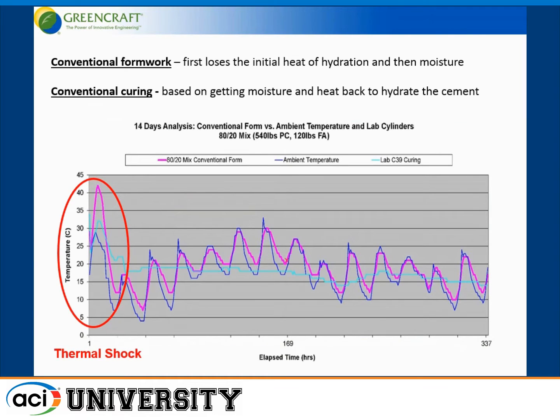Here's a chart of a project that we did in Atlanta. What we have here is conventionally formed concrete. There's a disconnect, in our view, between the formwork being simply used as a mold, which in essence it is, and the formwork being to some extent the environment in which you place the concrete in its infancy. And what we have here is an 80-20 concrete mix, 540 pounds of Portland cement, 120 pounds of fly ash type F, and you place it in the form, and as the hydration reaction gets going, you reach peak temperature, in this case about 42 degrees Celsius, in very short order, in 12 to 18 hours.